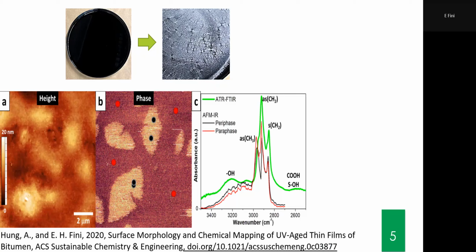So I caution you, if you look at aging and get into the study of aging, be careful of the depth variation, because as I showed you here and we published in this paper in ACS, the depth, going downward inside the bulk, is a different story than on the surface. Clearly shown here with the two spectra, one on the top, one in the bulk, and they are very different.